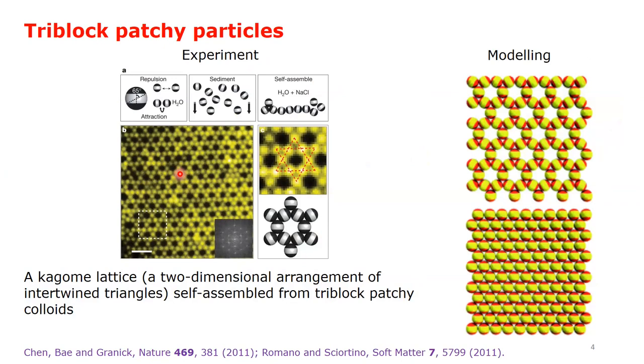Here, the designer colloidal building blocks have equal-sized attractive patches on the poles across a charged middle band. Upon screening the electrostatic repulsion between the particles by throwing salt into the medium, the self-assembly was observed.